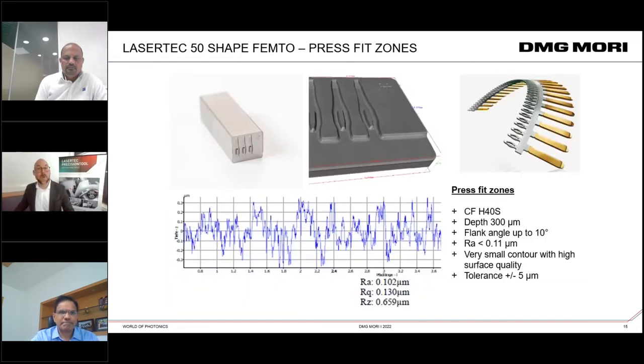So let's have a look at where these femtosecond lasers can be used. This is what we can see, for example, for these press fit zones. In the center picture and on the left hand side, you see a tungsten carbide press tool, and the shape we can see here in the microscopic picture is what gets laser ablated with a femtosecond laser. The material in this example is a Ceratizit tungsten carbide, and the surface finish we can achieve on that contour by laser ablating with a femtosecond laser is Ra 0.1. How would you do that workpiece conventionally? I tell you, the industry so far is still using HSC cutting or EDM machining. But the machining time and the tool wear related to that are more or less exploding the cost. By doing this with the laser, it probably only takes a couple of minutes.